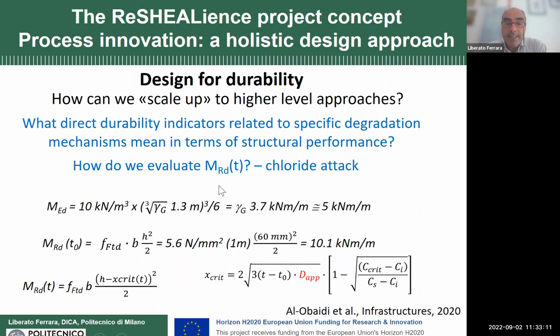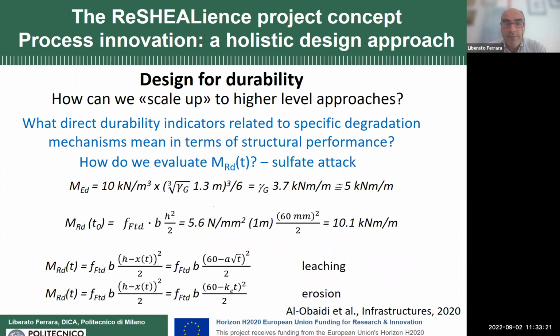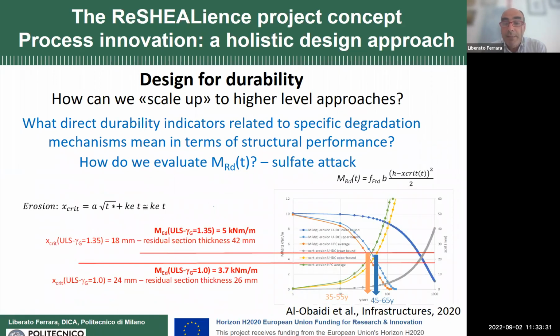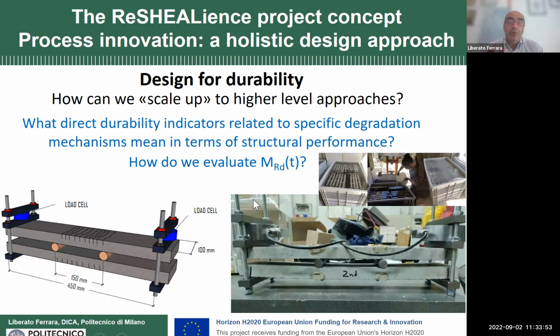But in the end, we just had to implement the chloride penetration mechanism, for example, or the sulfate, into the structural design equation. We lose progressively something. This was for chloride, this is the Fick's law, and this is for sulfates, depending on whether you have leaching only or erosion as well. But in the end, we realized that even with this material, even with this very, very severe assumption of removing the layer, we went from the orange or the blue curves, which are for ordinary concrete, to a much, much lower degradation of the structural capacity over time in our materials. Then we wanted to be more, intellectually earnest, I would say.